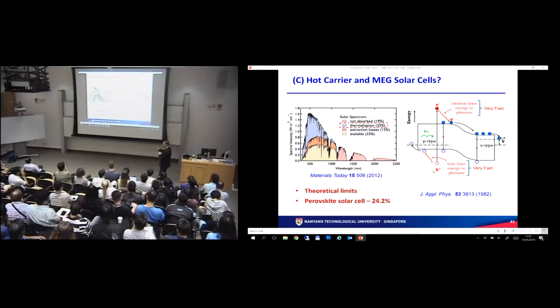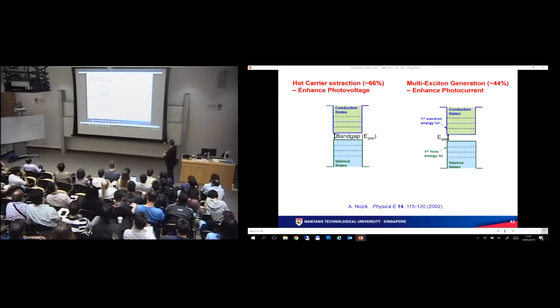Now, if you can harvest this energy before it is lost to heat, you have a way of increasing the efficiency of the solar cell. So that is the motivation behind trying to harvest these hot carriers. Now, there are two concepts where you can try to do this. One is to extract the hot carriers directly, in what is known as hot carrier extraction. That gives you a theoretical efficiency of about 66%. That allows you to enhance the photovoltage. A second concept is based on multiple exciton generation. That is based on enhancing your photocurrent, and that increases your efficiency to about 44%, theoretical maximum.